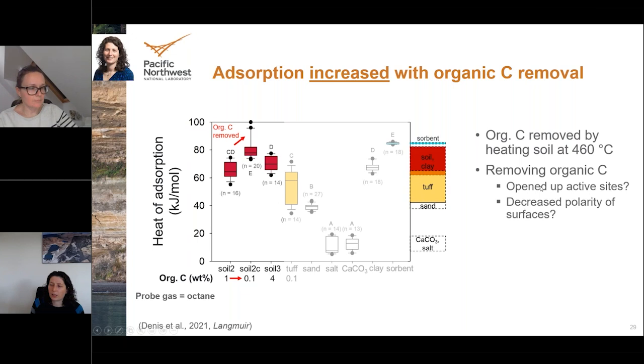But what we think could be happening is that removing the organic carbon maybe opened up active sites that were originally covered by the organic carbon. And now those active sites are available for the octane to adsorb onto. And then potentially there could have been an impact of decreasing the polarity of surfaces as well, making it more interactive. So that's just a few examples of how temperatures could affect it.